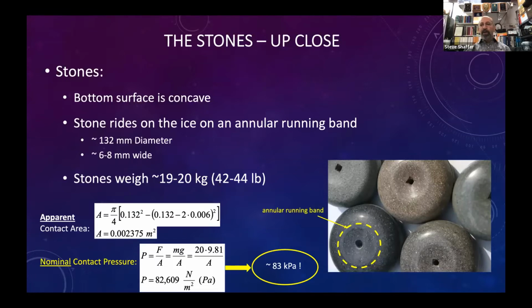The bottom of a stone, if you ever turn one over, is concave, sort of like a dinner plate. So you can see that there's an annular running band. That's this yellow dotted line I've shown here. It's about 5 inches in diameter. They vary between 4 and 6, and it's about 6 to 8 millimeters wide. So if I use those dimensions and the fact that a stone weighs about 20 kilograms, I can calculate an apparent contact area here of 0.002 meters squared. I can take force over area. That's easy enough.